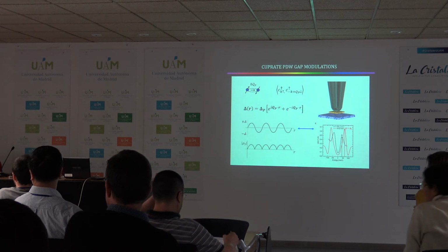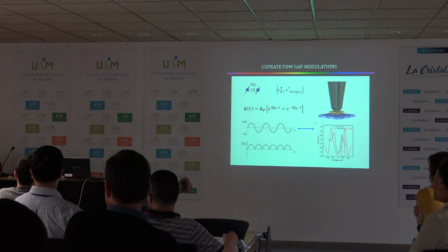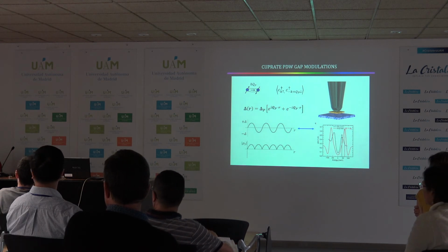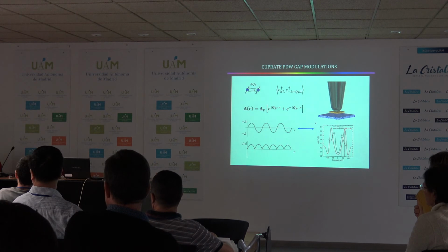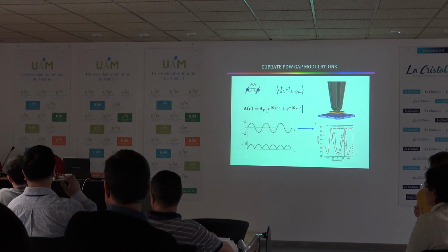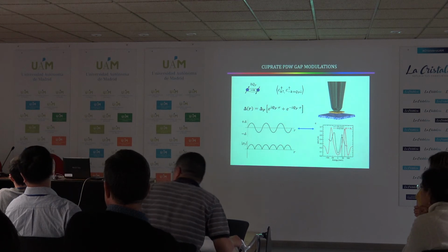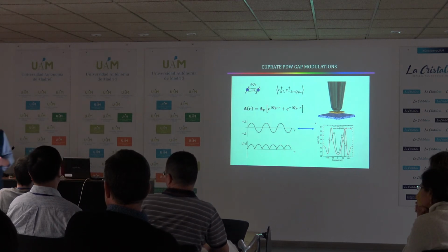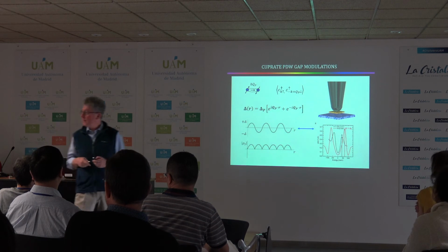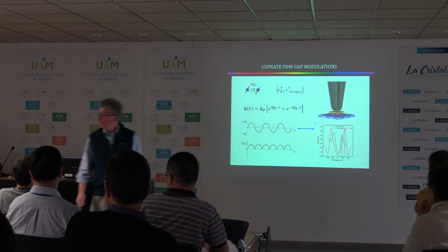Well, in both cases, since the superconducting order parameter breaks gauge symmetry, but the charge modulation does not, the elementary thing is that the Q vector of one has to be twice the Q vector of the other. That would be the simplest thing. If you scan Josephson on niobium diselenide, you should find 6 new peaks in the Josephson channel, at half the Q values of the CDW.